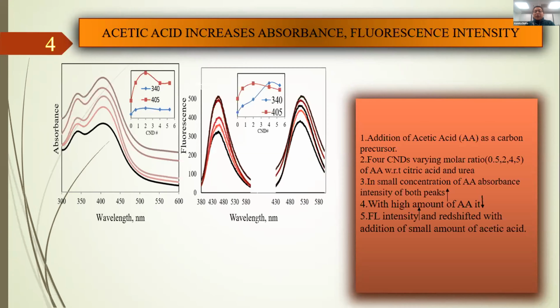At a small concentration of acetic acid, the absorption intensity of both peaks is increased. It is quite unexpected and unnatural. But with a higher amount of acetic acid, it again started to decrease. It may be due to the condensation of acetic acid to form acetic anhydride. Fluorescence intensity is also dramatically increased and significantly redshifted with the addition of acetic acid.